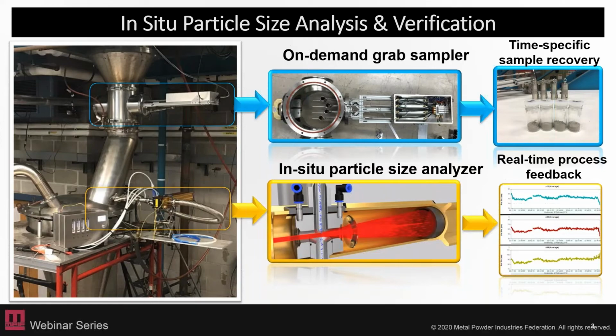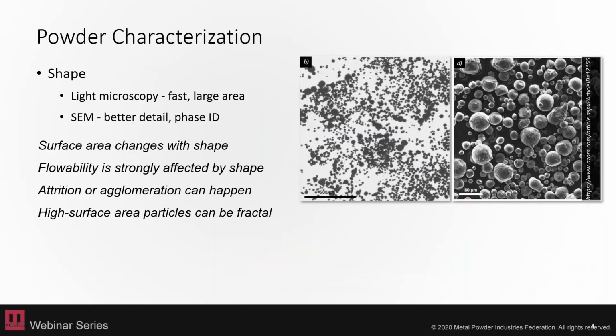When looking at powder characterization, shape, as I mentioned, is also very important. For getting an analysis of your shape, you can use light microscopy, which is really fast and gives you a large area, like in the image on the left. Or you can also use scanning electron microscopy, which gives you better detail and can give you some phase identification through energy dispersive spectroscopy. Again, your surface area changes with your shape, your flowability is strongly affected by it, and your attrition or agglomeration can happen.